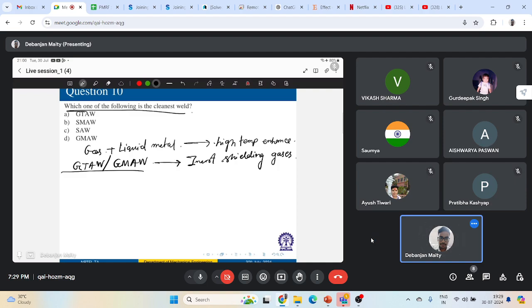Now, what happens in shielded metal arc welding? In shielded metal arc welding, the flow of gas in that process is not as well directed towards the weld pool as the flow of inert gas in gas tungsten or gas metal. Right? The protection is adequate for the weld metal, but is less effective. Because this is less effective, that results in higher weld oxygen and nitrogen concentration levels. Right? You can have some kind of self-shielding arc welding also.